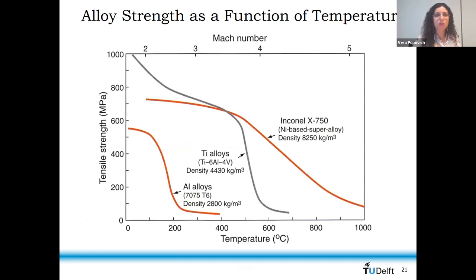Here you see another interesting example of low strengths. And besides this, the high temperature resistance in terms of strength, so you see the tensile strength with respect to the temperature, yeah? So aluminium alloys is definitely light, yeah? So that's a good example. It could be used for casing, but it's not really high temperature resistant. You can see a very sharp degradation in strength with temperature. With titanium alloys, it's somewhat better, so it shifted to higher temperatures.